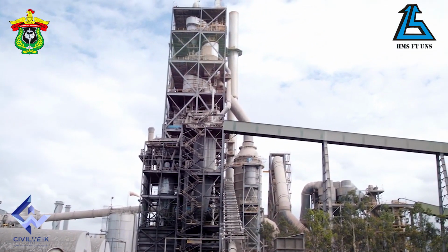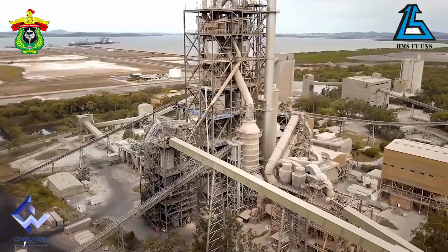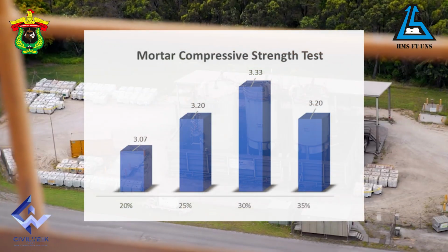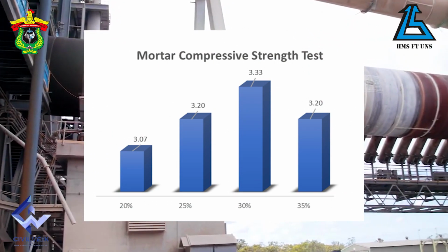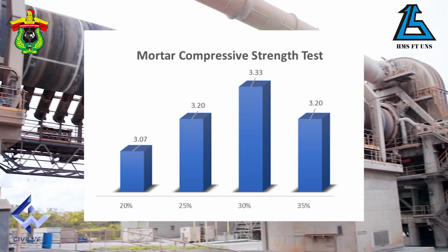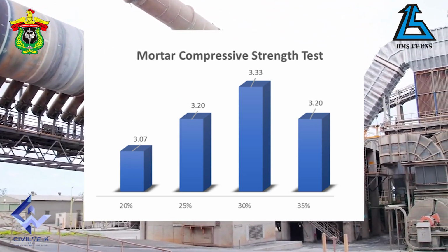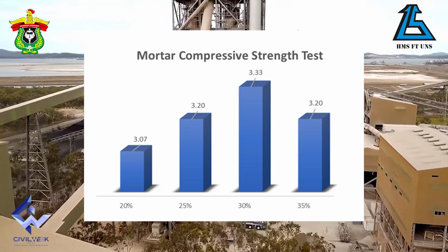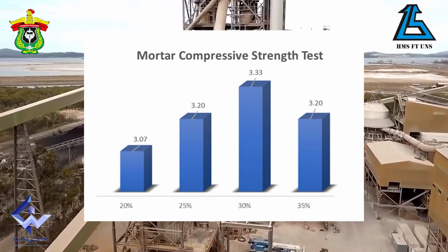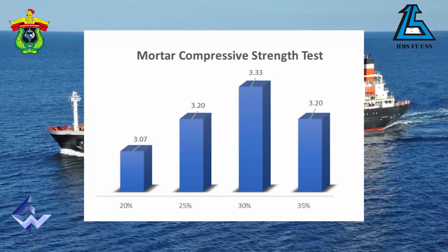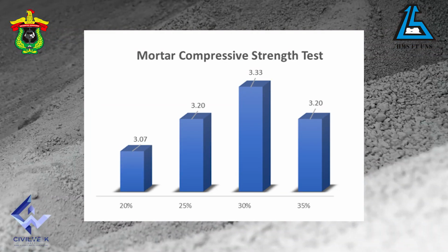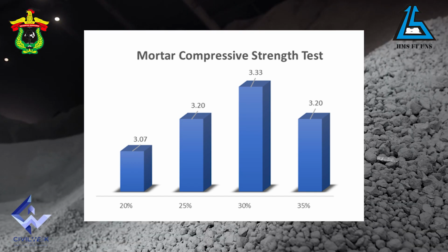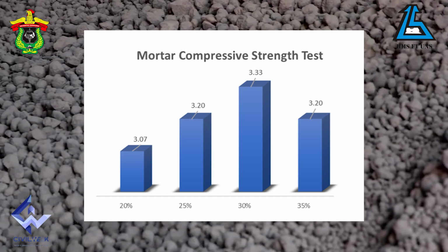Based on the result of the one-day-old mortar test that has been carried out, the research shows that the highest compressive strength is produced by the variation of 30% with a strength of 3.3 MPa. And by that, we choose variation number 3 with 30% replacement of cement. Step 2, making concrete in the International Concrete Competition Civilweek 2021. This concrete is designed to be high strength, economical, and environmentally friendly.